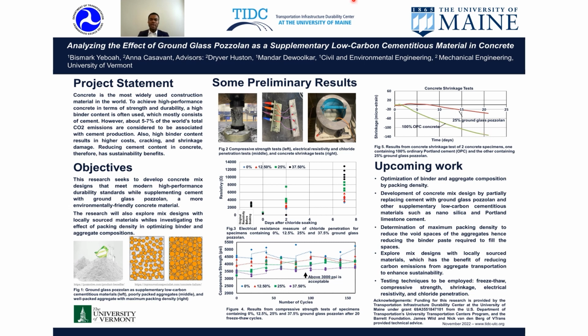So these are our upcoming works. The research seeks to optimize binder and aggregate composition by packing density, and it will also develop concrete mix design by partially replacing cement with ground glass pozzolan and other supplementary low-carbon cementitious material, such as nano-silica and Portland limestone cement. The maximum packing density of aggregate will be determined to reduce the void spaces of the aggregate, hence reducing the binder paste required to fill the spaces.